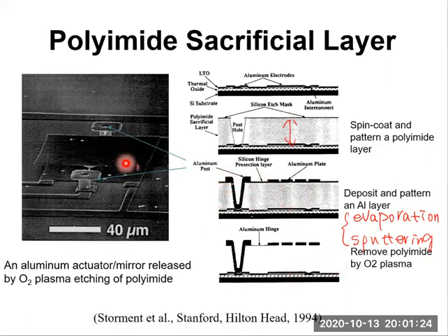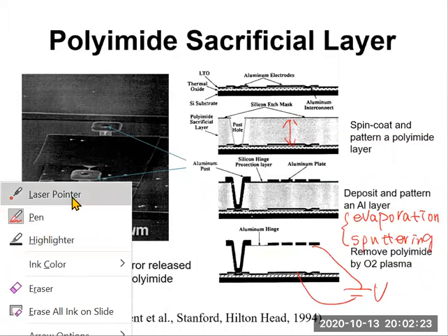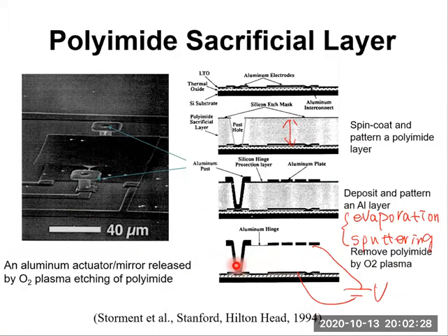Finally, this aluminum plate, aluminum mirror, is released by removing polyimide. The polyimide underneath is removed by oxygen plasma etching. Note that this mirror can be actuated by applying voltage between the plate and the bottom substrate. So we can apply a voltage in between, and this voltage can actuate this micromirror, to tilt this micromirror. So the mirror is driven by electrostatic force. So in this example, polyimide is the sacrificial layer and aluminum is a structural layer.